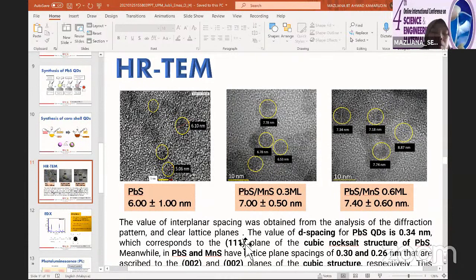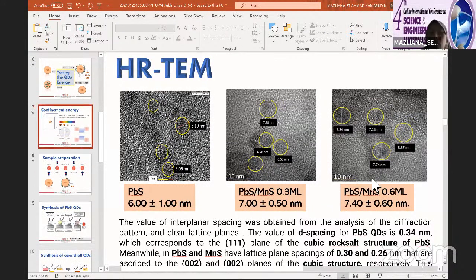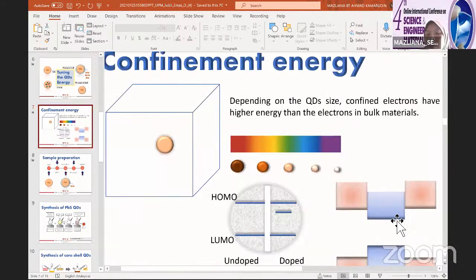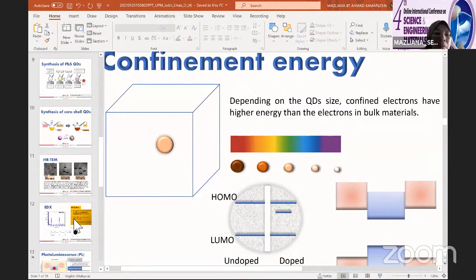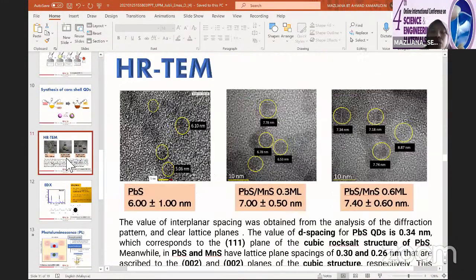Then it didn't work, because in order for us to synthesize even smaller, it's even harder. So what people can do is go for doping, or go for core shell, with the purpose to tune the energy. That is the motto of why people go to the core shell. But another motto is to trap the carrier inside the region. For example, my work is in type 1. In order for us to trap the carrier, we can put a shell layer so that it will sit inside the core region. That's why people go for the core shell or core shell shell.